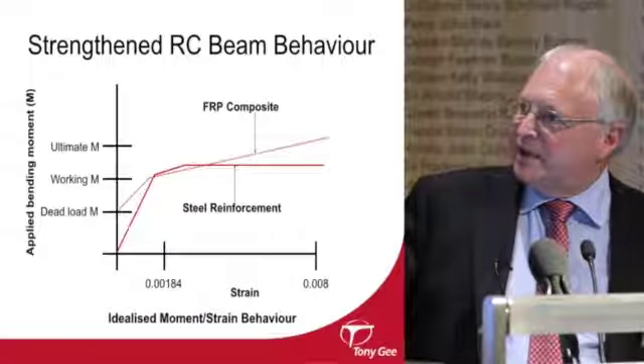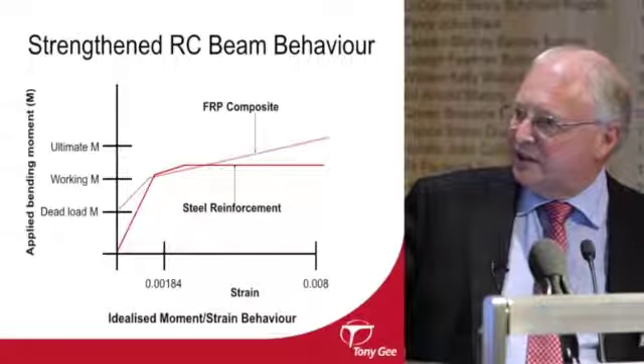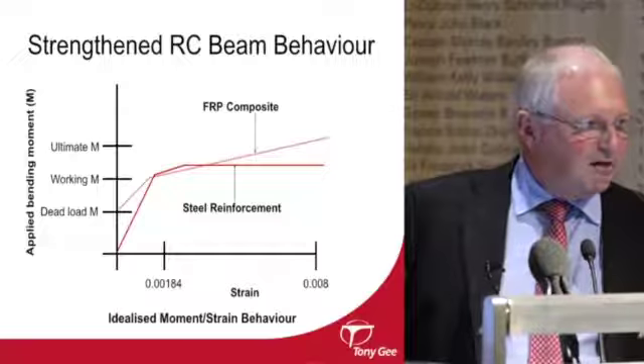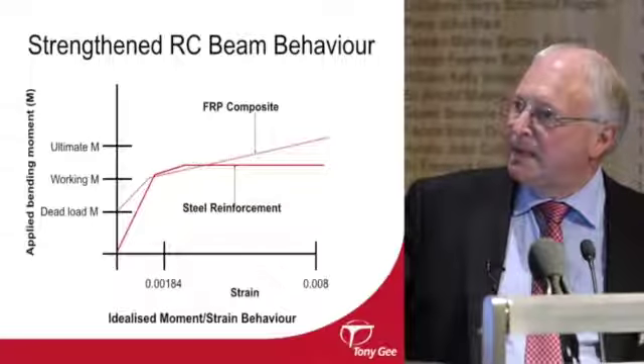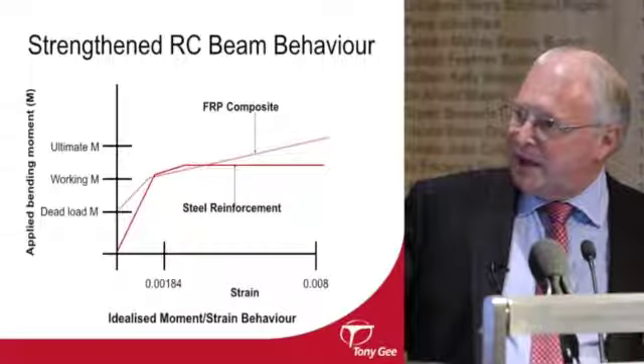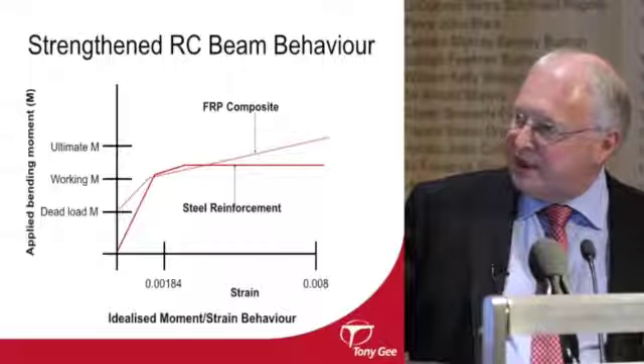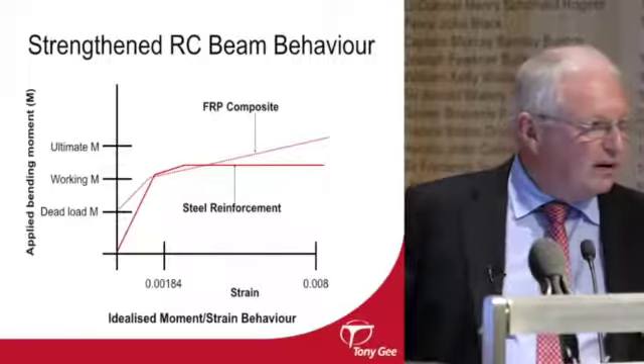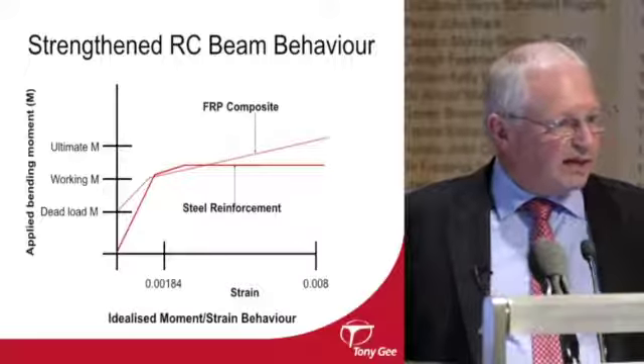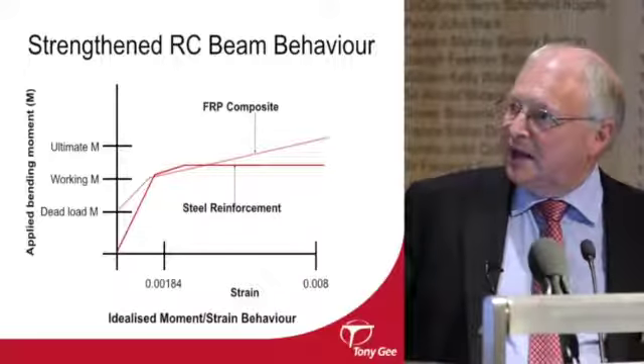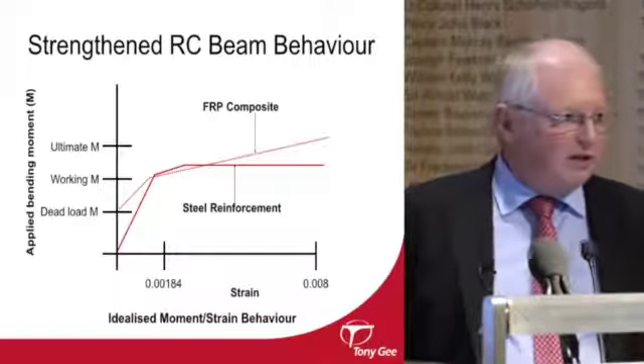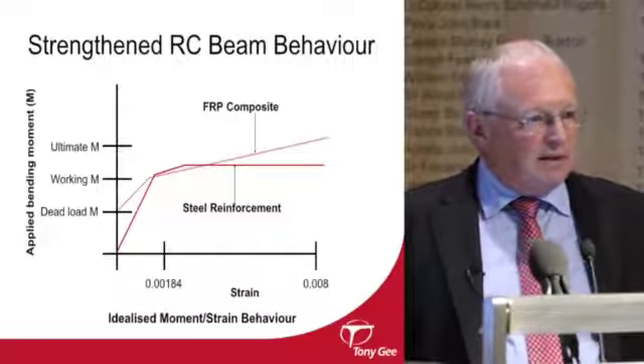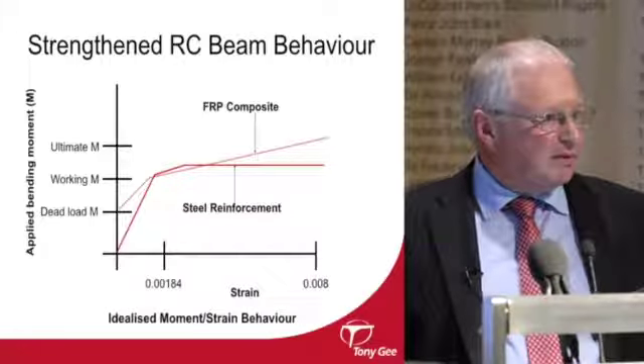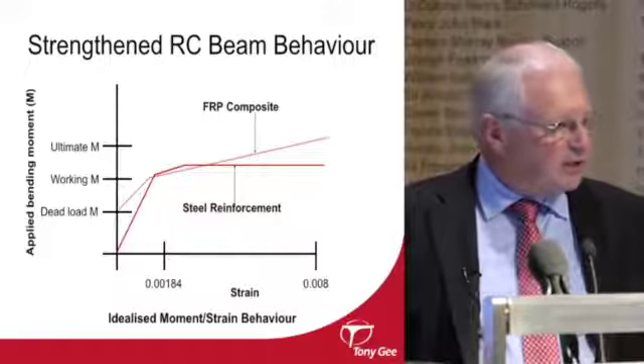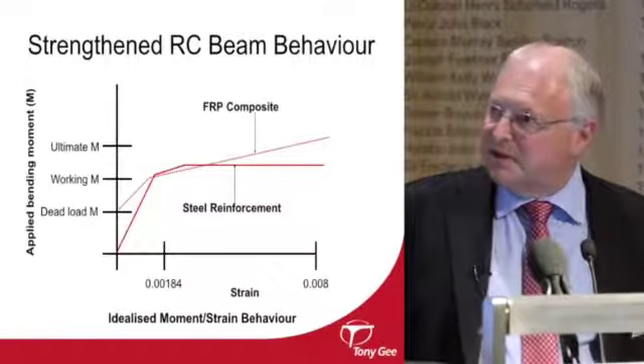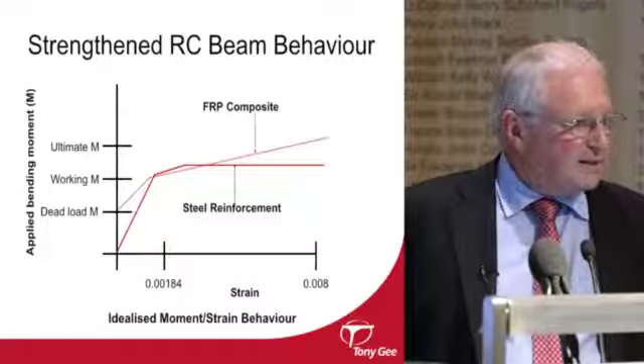And at this point, every increment in the loading cycle is taken by an increase in strain in the FRP. So you need to be a bit careful that you're not operating in this zone under normal working loads, otherwise your deflections are going to get very high. And if you do need that degree of strengthening, then what Fabio is going to talk about next, post-tensioning systems, is probably something that should be considered.